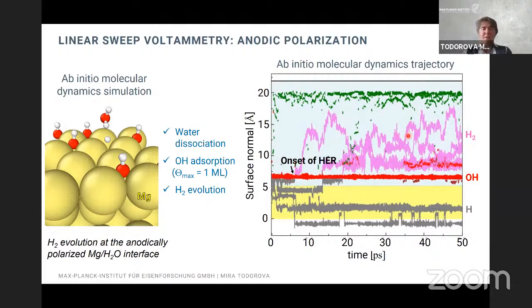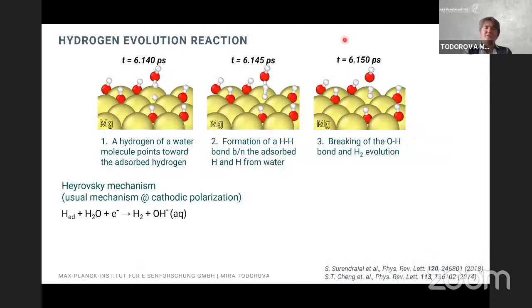When we look at more details, here are a few snapshots of the reactions. What we see is that there is a water molecule which interacts with the adsorbed hydrogen on the surface and eventually forms an OH and a hydrogen molecule. And this is very reminiscent of the Heyrovsky mechanism, which is the usual mechanism known for cathodic polarization. However, in this mechanism, typically an explicit electron is required in order to drive the reaction, and therefore it was never considered in the studies of the anodic corrosion of magnesium.